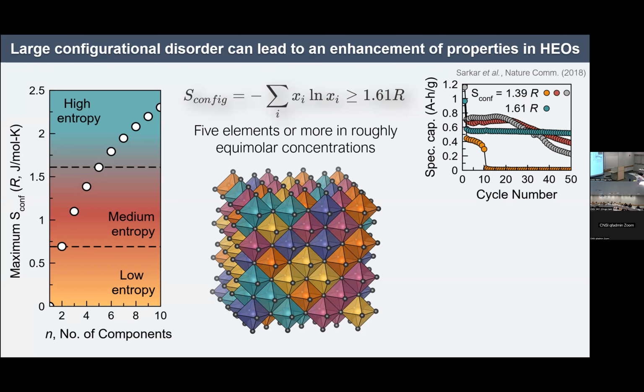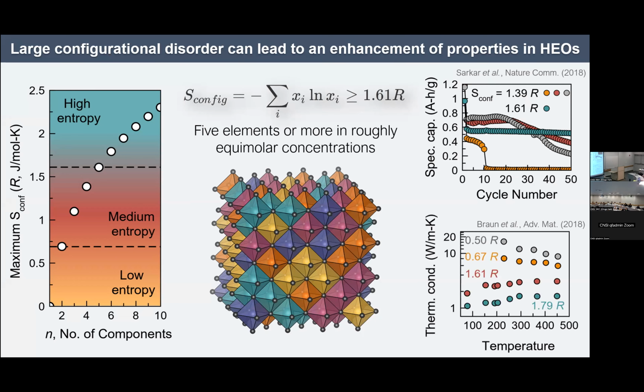Another example is from the field of thermoelectrics, where we look at the thermal conductivity as a function of temperature. Notice that this is on a log scale, where I'm plotting compounds with increasing configurational entropy, up to one that actually has 6 components. We see a systematic suppression of the thermal conductivity, which is useful if you're trying to maximize your thermoelectric figure of merit, ZT. One remarkable thing to point out is that these materials are crystalline, but this lowest thermal conductivity material has a thermal conductivity that is actually lower than the amorphous limit.